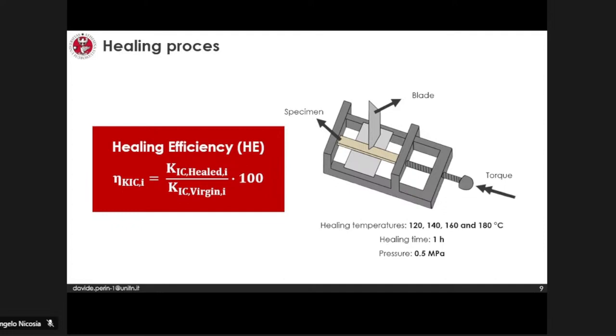So one 10 millimeter per minute, the other one 1.5 meter per second. By evaluating the K_IC of the virgin material, then I heated everything inside the oven in an iron vise with 0.5 megapascal of pressure at different temperature, and then I retested, obtaining therefore the K_IC of the healed specimen. The ratio between these 2 K_IC is the so-called healing efficiency.